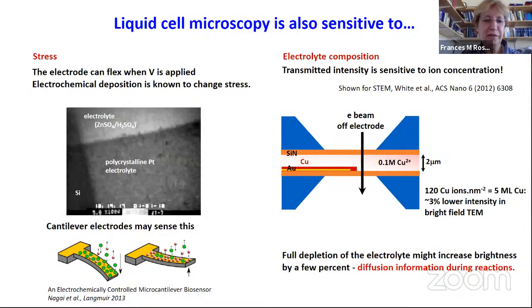So let's move for the last few slides onto some really speculative things that I think could just be fun to think about, even if we never ever do them. As you know, electrochemical deposition can change the stress state of materials. Microscopy is very sensitive to small changes in stress or orientation, and so it's possible with a cantilever electrode to measure stress as you do a deposition experiment. It's possible to measure the chemistry of the electrolyte because the transmitted intensity is sensitive to the concentration of especially heavy ions in solution. And so you can see some effects of depletion of electrolyte in real time during the movies.